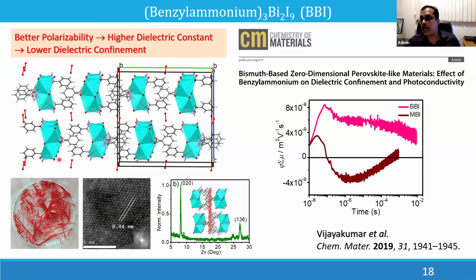in the conductivity property, in the photoconductivity. We measured the photoconductivity of this material. And you can see in the methyl ammonium based system, the photoconductivity is low, and we were able to get like 2 to 3 times higher photoconductivity in the case of this benzyl ammonium based material.